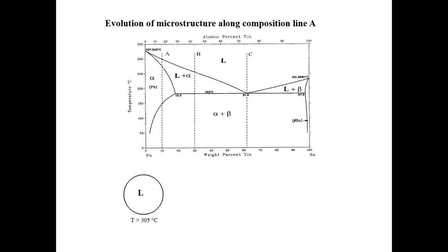So I start with a liquid. If you take a small observation window and look at the system, you're going to see a homogeneous liquid state. There's no microstructure. Now, what happens if I lower the temperature and get into the two-phase coexistence region right here? What are you going to see in terms of the so-called microstructure of the system? So liquid state with some alpha phase. You're going to see a majority of liquid, if you look at this at the top, at high temperature, and there will be some small alpha phase forming in the system like this. It's very similar to the germanium silicon.